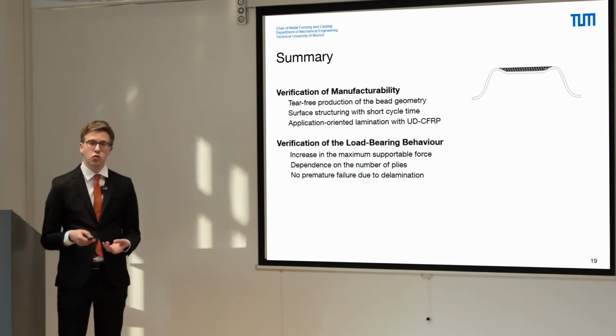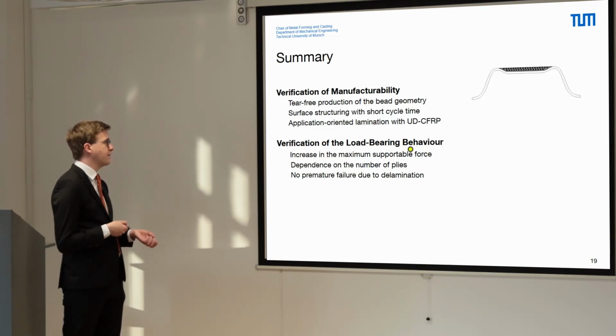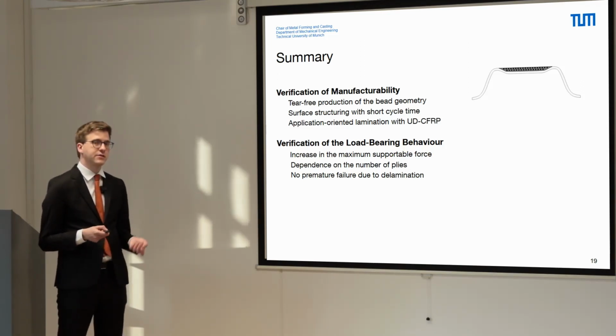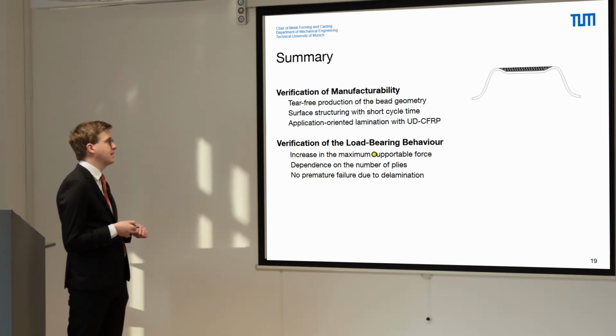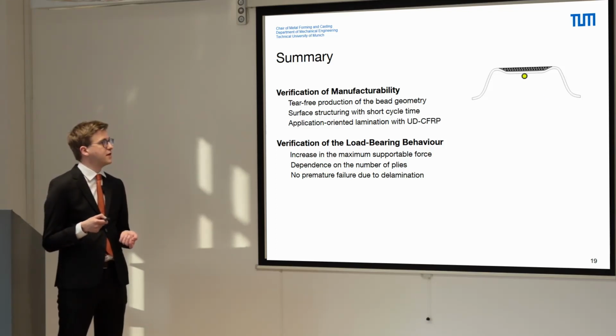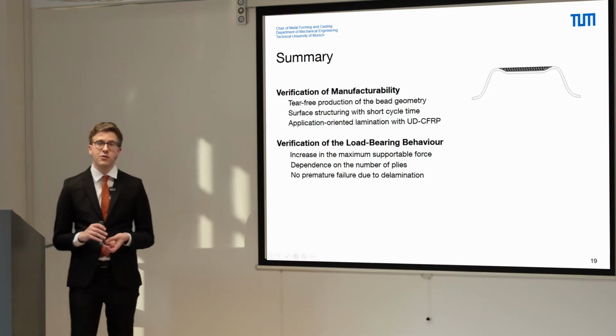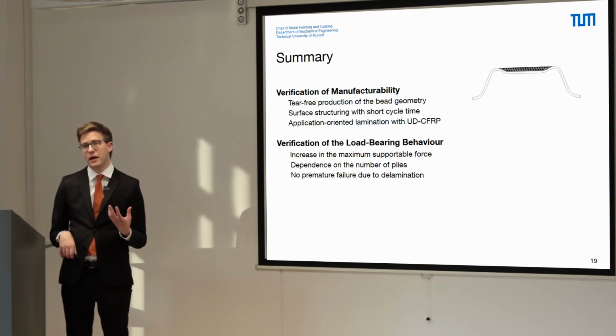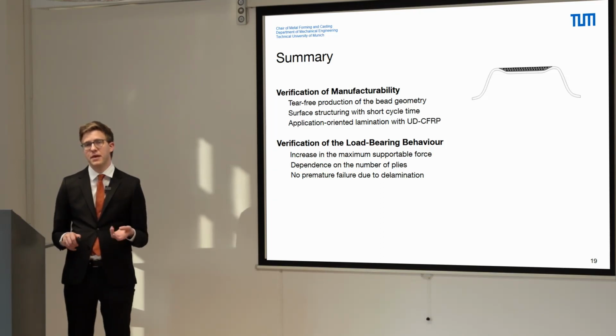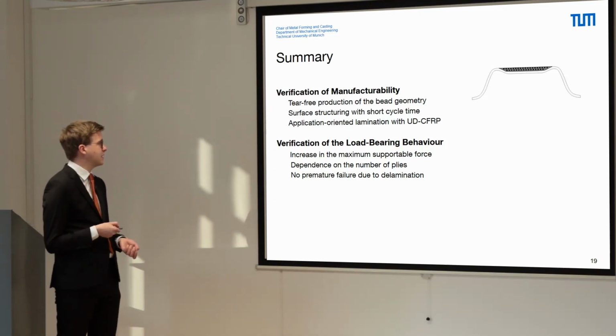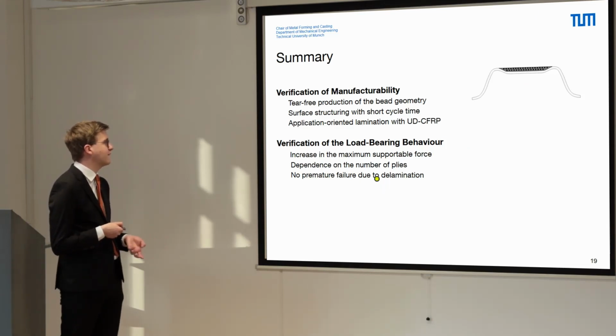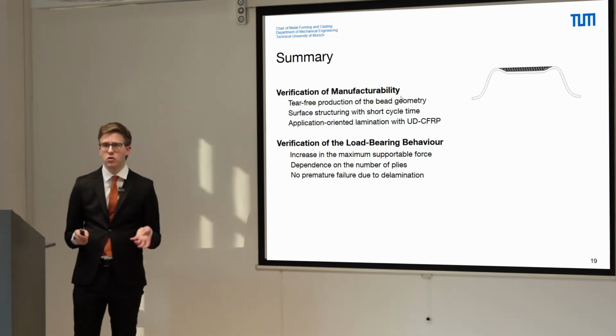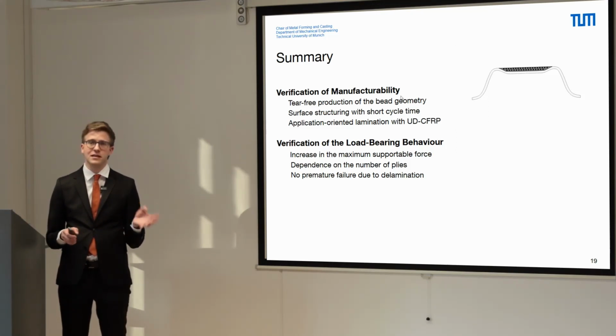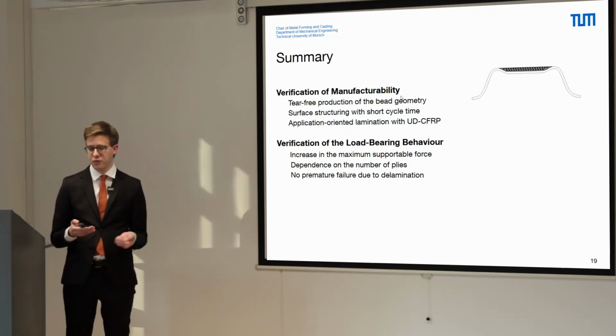The second main goal was to show the load-bearing behavior of our hybrid beads, showing that there's an increase in the maximum supportable force, and that this increase is dependent on the number of plies laminated on the top surface of the beads, which is a necessary condition for the design of load-dependent component variants. And last but not least, we show that there's no premature failure due to delamination using these structuring strategies, so no additional interlayer such as an adhesion promoter is needed for these hybrid beads.